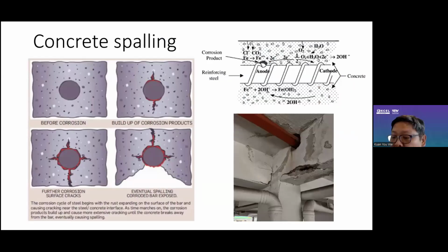And there is an issue that has been overlooked by the industry, which is the impact of corrosion. Typically at the swimming pool, chloride-containing water enters into the concrete and starts to corrode it. Corrosion of the reinforcement steel bar causes the volume to expand due to the byproduct of the corrosion, and it will crack our concrete as well. So please bear in mind that if our concrete suffers from corrosion, even though we waterproof on top of the existing building, the cracking mechanism still continues, like the battery in our torch light. Even though we don't turn the torch light on, the battery will self-consume by itself. Likewise with the corrosion matrix in our reinforcement steel bar.